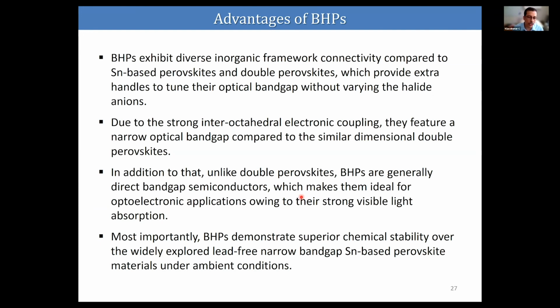And due to the strong interoctahedral electronic coupling, they feature a narrow optical band gap compared to similar dimensional double perovskite. And in addition to that, unlike the double perovskite, these materials are generally direct bandgap materials. That is an advantage, which makes them ideal for optoelectronic applications because of the strong visible light absorption. And most importantly, these bismuth-based materials demonstrate superior chemical stability compared to the lead-free tin-based materials under ambient conditions.